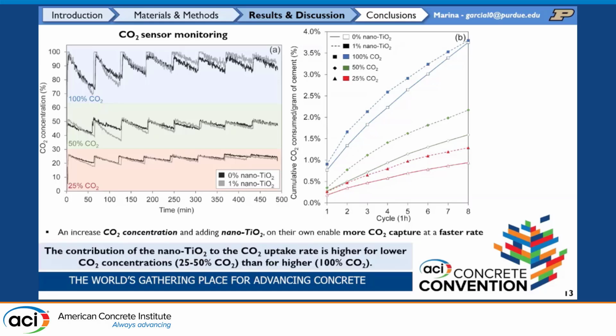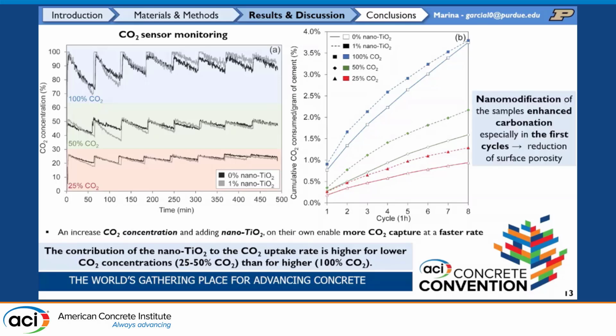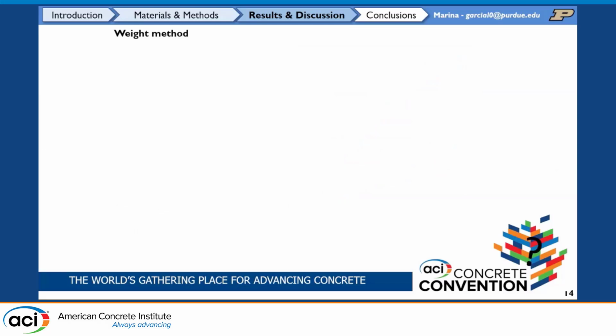However, the contribution of these titanium dioxide nanoparticles in the CO2 uptake rate was higher when we exposed it to lower CO2 concentrations. As you can see here, this difference between the green and the red lines, which are the lower concentrations, is higher than this one right here. And we think this might be due to the nanomodification of the samples enhancing carbonation at the beginning of the cycles, due to the reduction of porosity preventing it from further happening.